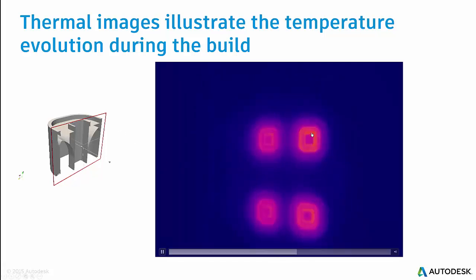As we move into these thicker sections, we see the temperatures get very hot. We don't have uniform temperature distributions throughout this build process, and that can cause problems with non-uniform material properties, non-uniform microstructure. Lower on these walls, you might have problems with the material not fully fusing where we weren't getting very hot.